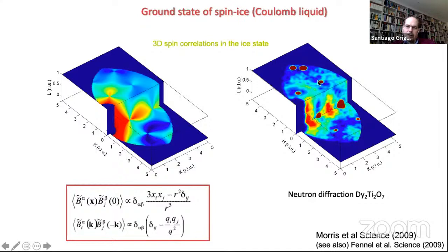I know the data is not pristine, but you see that the main features are essentially there. So you see that the parts where you expect to have maximum intensity is where you get maximum intensities, and these parts where you get these characteristic pinch points that are talking about these correlations are essentially parts where you get less counts. So it's going in that direction.